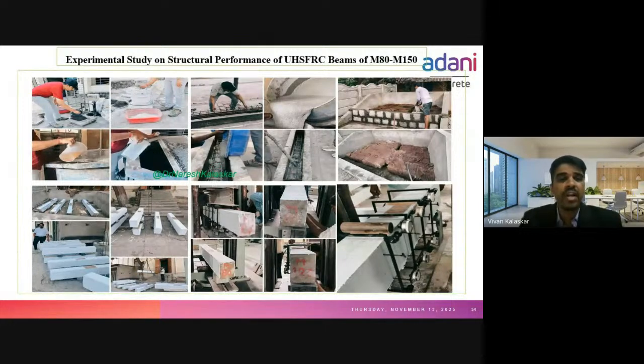These are a few photographs where I'm measuring the steel fibers, mixing the alcofine, and introducing the reinforcement cage in the beam. And one exceptional and good design parameter of this concrete is that UHPC is usually cured with heat curing, thermal curing, but we have cured all these specimens in normal curing at 28 degrees plus or minus 2 temperature. So for curing you do not require any special setup. You can manufacture your concrete and cure it as per your site condition. You will get UHPC results. Gunny bags were used to maintain the moisture.